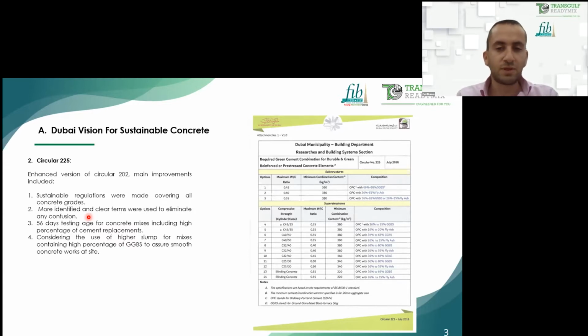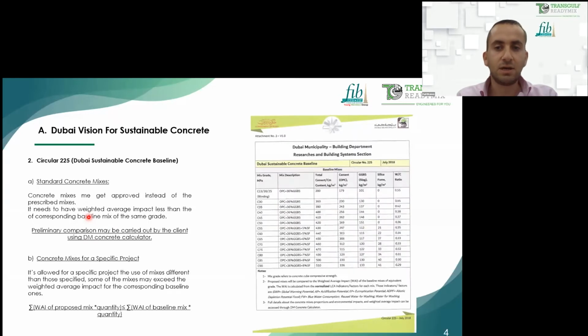One more improvement in this circular is establishing the baseline mixes. These baseline mixes allowed the design engineers in the industry to be more creative, to propose mixes beyond the guidelines, as we discussed before. But they set sustainable baseline mixes. These mixes start from 15 MPa up to 90 MPa, and for all these options, the weighted average impact is calculated based on the life cycle assessment.